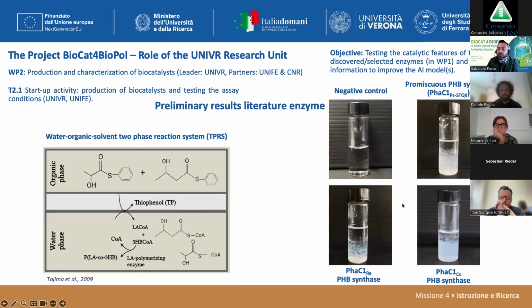These are some visual data. This is a negative control, and as you can see, for the 3 enzymes we have tested, we got the polymers, which we have also characterized in composition. Most of the data confirm that for most of these polymers, the main building block is hydroxybutyrate. So even the synthesis enzymes reported to be promiscuous failed in the introduction of lactic acid into the chain.